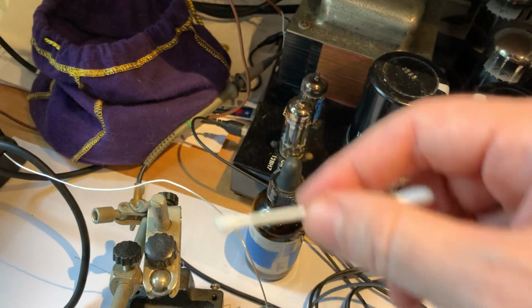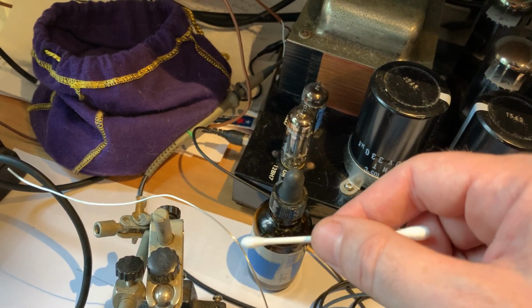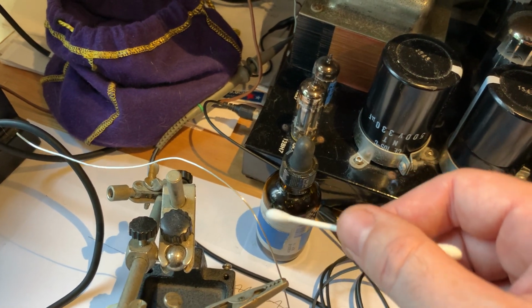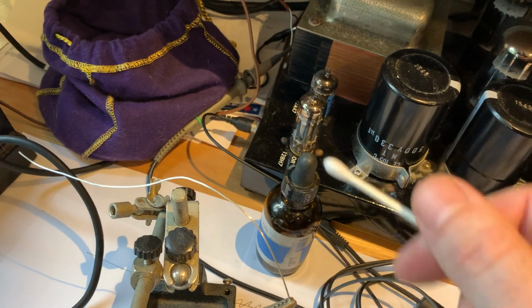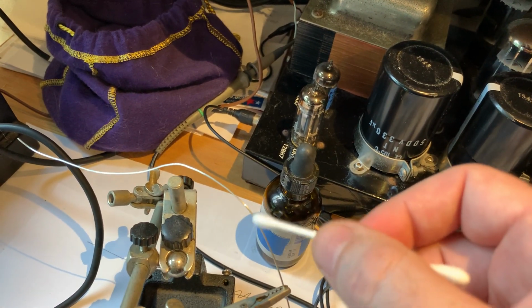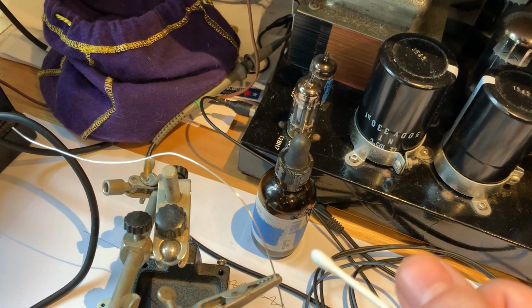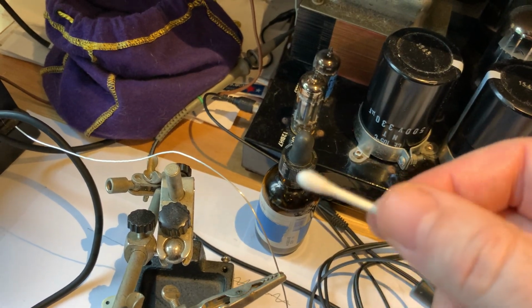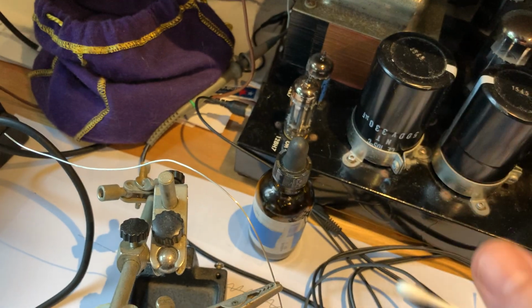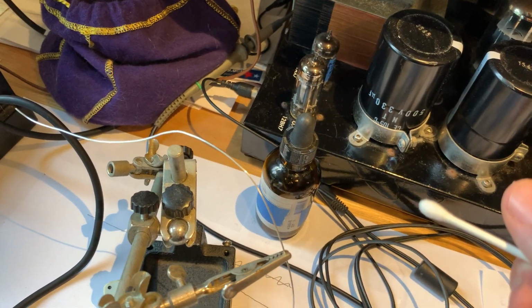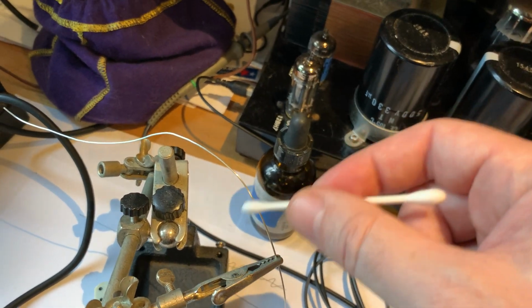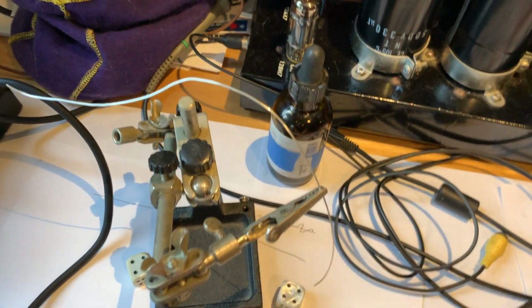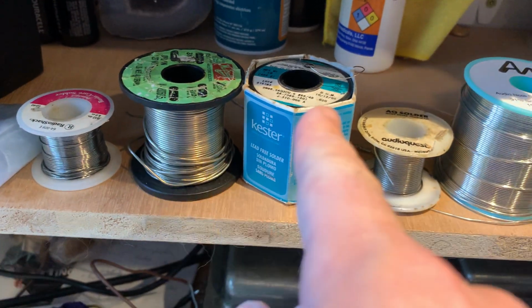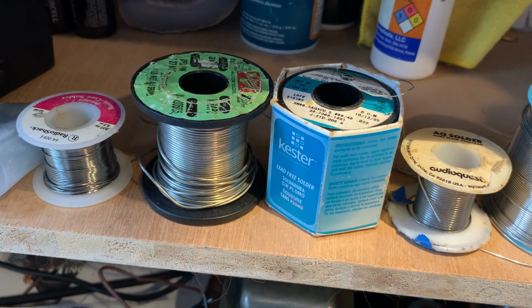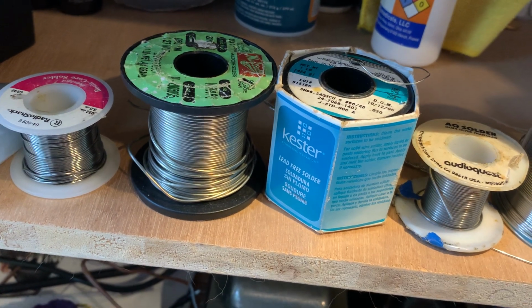When your equipment is conducting electricity, it will slightly carbonize on the surface. So when you look at an older amplifier, you will see some black spots on some of these solder joints, and that's carbon deposits. That will cause low-frequency noises, hiss and background noise. So as amplifier maintenance, just dunk it and clean those joints. Of course, it's much harder to do that when you have an older amp or an amp that's already pre-made. If you do the joint right away and clean it up, you don't have to worry about that. If you use this method, you will have absolutely zero issue working with even the hottest melting temperature solder, and you will not destroy any components.